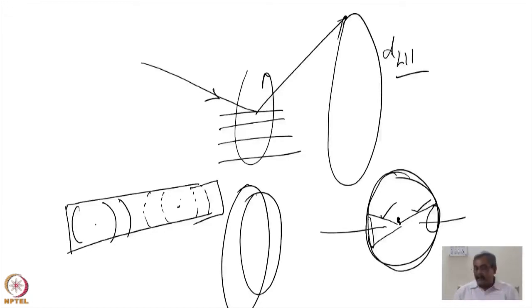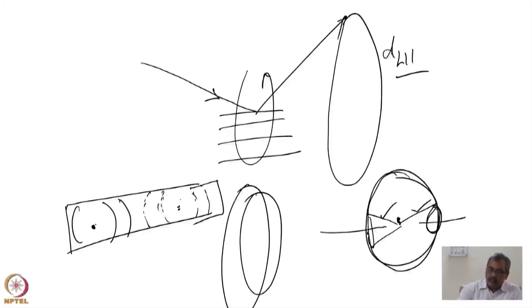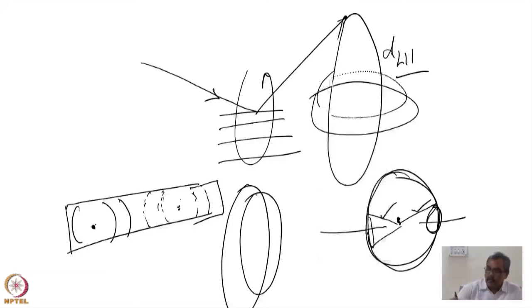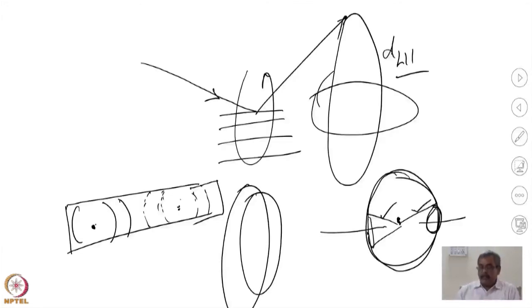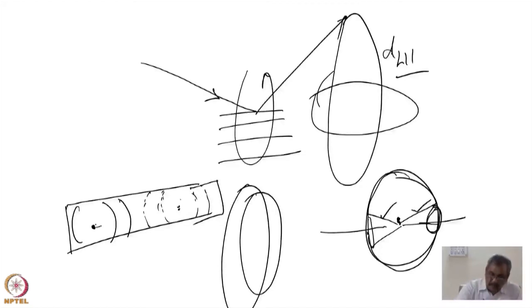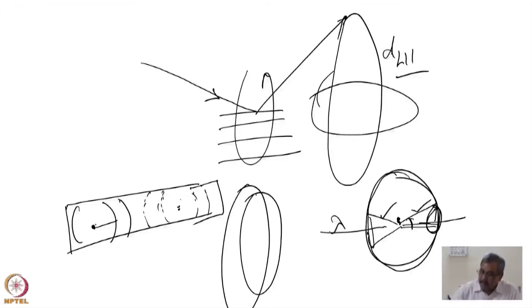When I develop the photographic plate, I see circles corresponding to various d-spacings. Those near the exit slit are low-Q values and more intense; those near the entrance slit are less intense due to the form factor in X-rays falling off. The photographic plate intercepts part of each Debye-Scherrer cone. Knowing the radius of each circle and the radius of the camera, we can calculate θ and hence the d-spacing for a given λ.